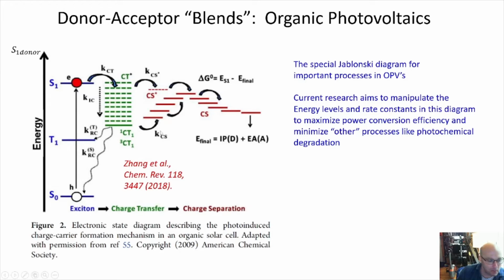And so there's a lot of thought in the literature that what really happens is you make the S1 exciton, and that dissociates into what's called a hot CT exciton, so a high energy one up here. So then there's a downward funneling from the hot CT exciton into one of the higher energy CS states, and then it's a little bit easier to make the truly charge separated state. And that's probably true for some choices of organic molecules in donor-acceptor photovoltaics, but not all of them.